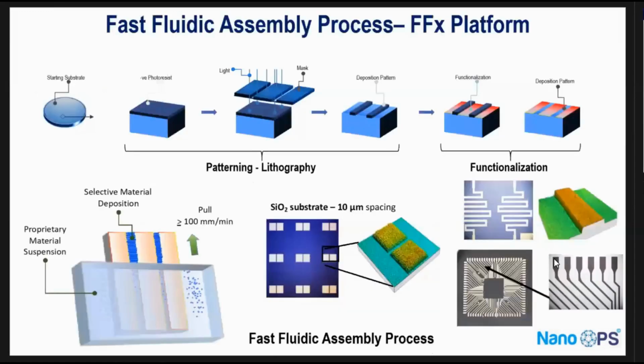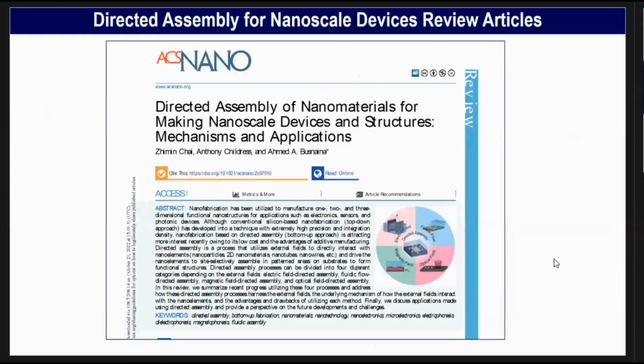Okay. So what happens if you want to do a large area very fast and you don't really have any conductor to apply an electric field like we did in the first technique? This is a fast fluidic assembly. Here you apply photoresist, and then you functionalize. You apply functionalization, hydrophobic and hydrophilic, and then you remove the photoresist, and then you do something similar to a dip coating process. This process takes about a minute. And then you can end up with a metal or dielectric or semiconductor pattern the way you want it, whether it's submicron, nano, or micro scale. And so you see some of these examples.